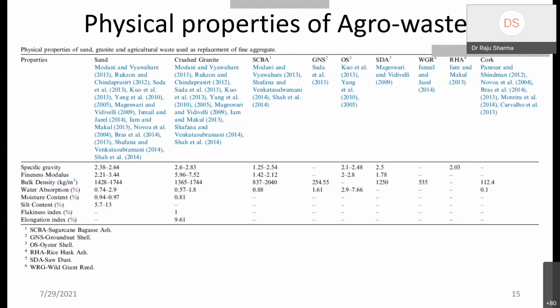And the surface area, you know that nucleation always starts from the surface when it comes in contact with the aqueous solution, and that particular surface creates the hydration product on the surface. And the higher the surface fineness, the higher the strength you can create, but it is not a straight line. It is related to the amount of binder as well, right? So you have to change the binder as well up to a certain percentage. After a certain percentage, at a fixed percentage of binder, your results may decrease, right? So this is not a straight statement.